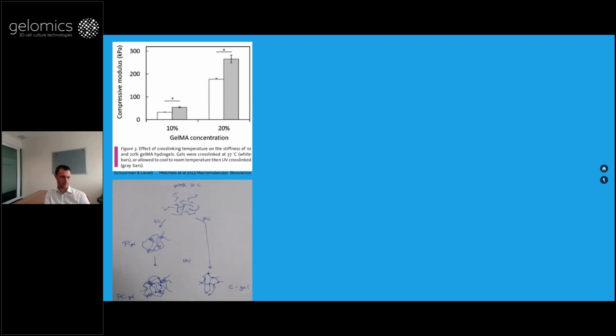Later I've been looking into this more. With a GelMA solution, you can either keep it warm and cross-link it straight away, so that you get a fully chemically cross-linked gel, or you can first let it gel physically. For example, in the fridge, it goes a lot faster than on the bench. In the fridge, you will first get a physical gel, as gelatin does, through triple helix formation, and then you can do the UV or visible light photo curing afterwards.